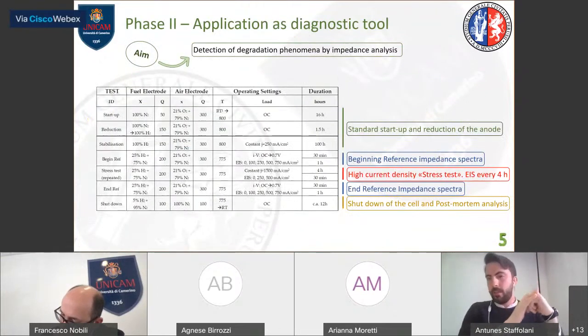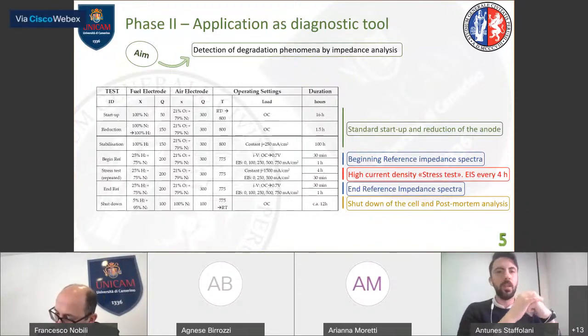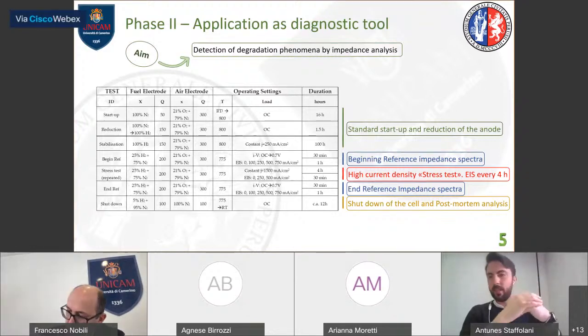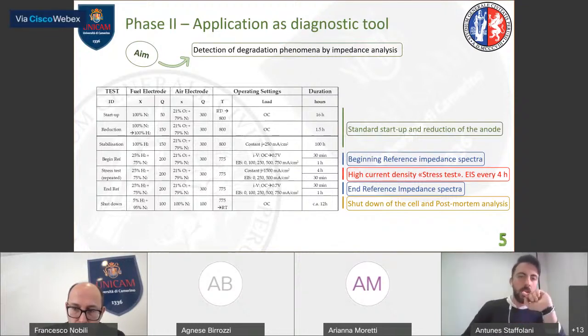Then we moved to phase 2. We decided to apply this electrochemical model to detect degradation phenomena in the cell. So we applied a stress test based on high current density, 1.5 amperes per square centimeter. And we acquired the impedance spectra every 4 hours during the stress test. And also we acquired the polarization curve and the reference impedance spectra before and after the stress test.